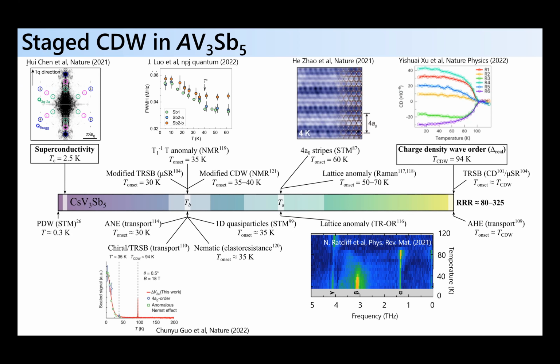And as you continue cooling down, then there's another temperature scale that seems to reflect more of what's going on in the electronic sector, where around 35 Kelvin, 1D quasi-particles appear on STM measurements, looking at their quasi-particle interference spectra. This is where the chiral or time reversal symmetry type features are seen in transport. This is also where in strained crystals, it seems, a nematic type of state turns on. And then as you cool further down, you enter the superconducting phase, and then there are claims of a pair density wave-like anomaly in the superconducting state.